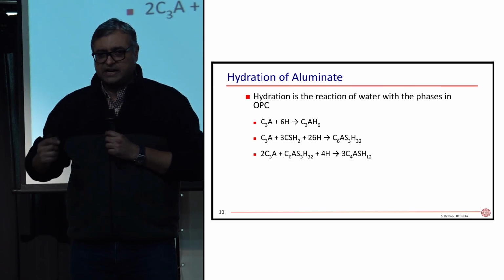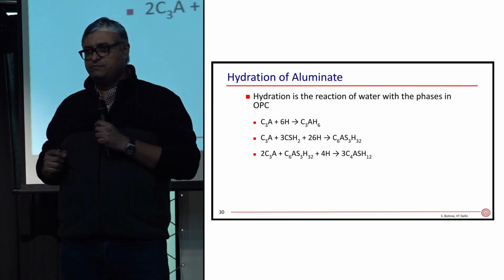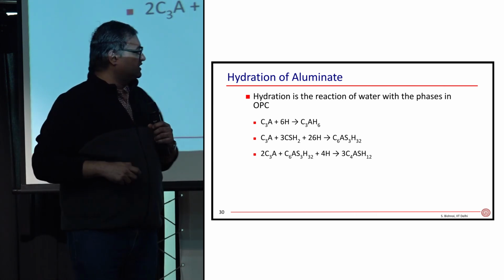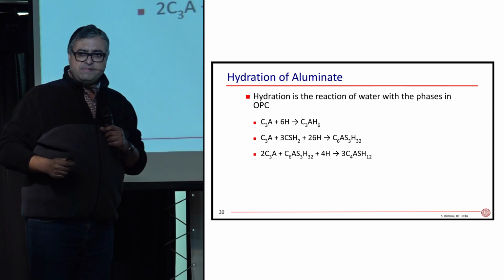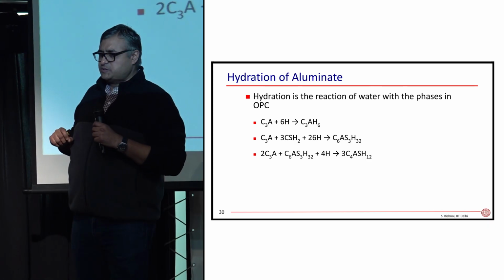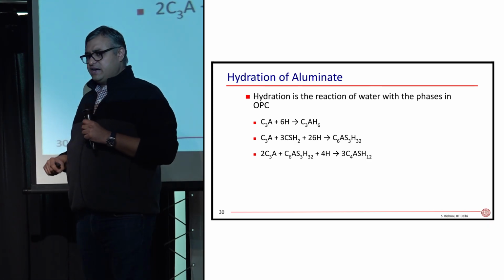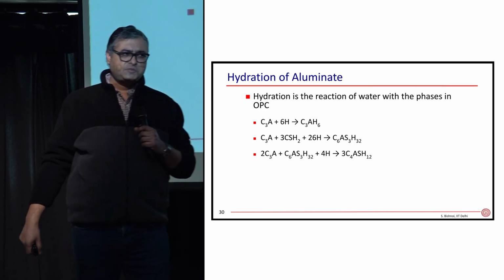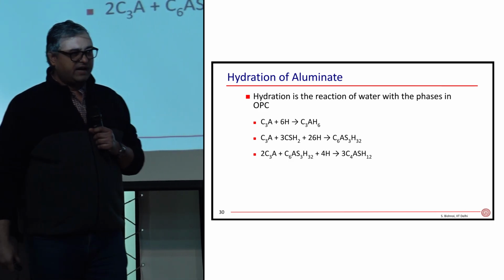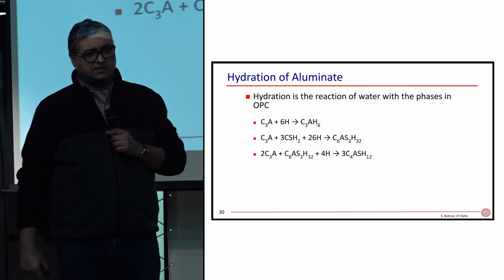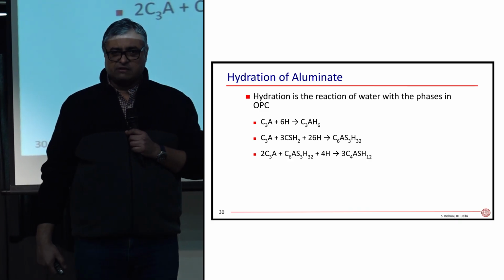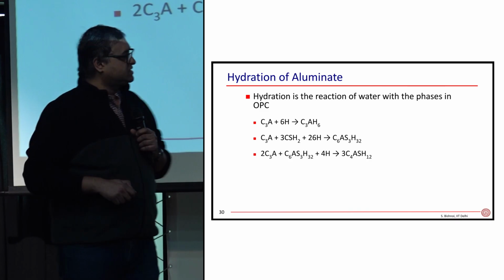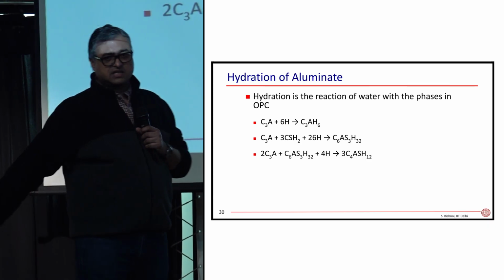So he's upset. He wants to have a certain amount of time to be able to work with the cement. So what they did was they mixed gypsum in the cement. Remember, we were grinding gypsum along with the cement? The reason why we are grinding gypsum with the cement is gypsum is ultra active. It dissolves very quickly, even faster than C3A. It goes into the solution, produces sulfate ions. These sulfate ions force the alumina to react with the sulfate.